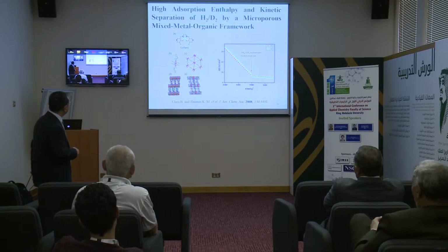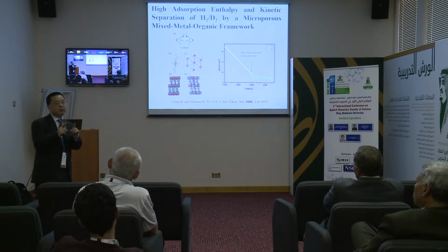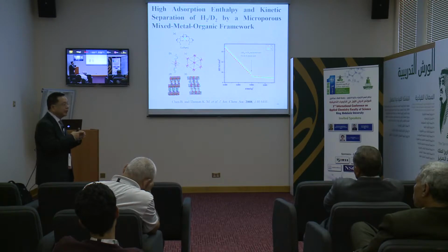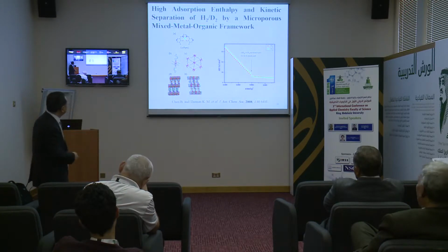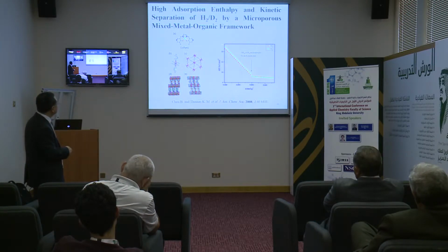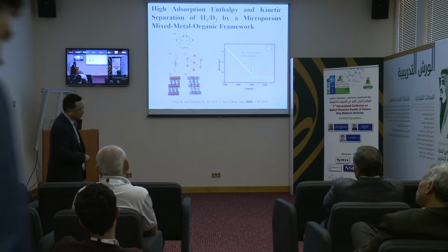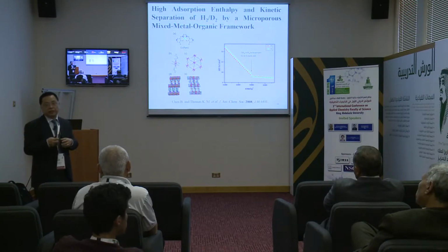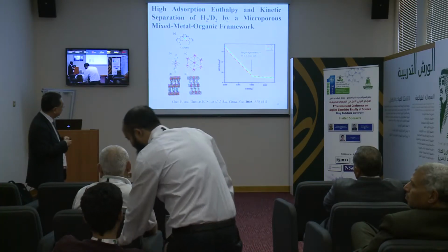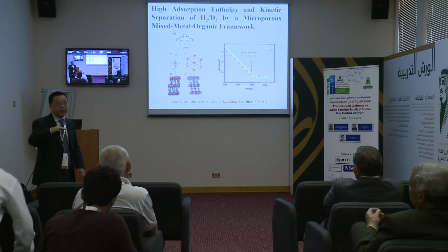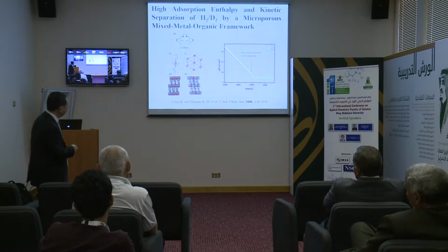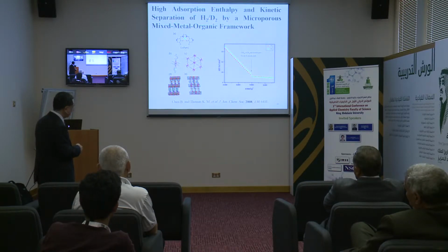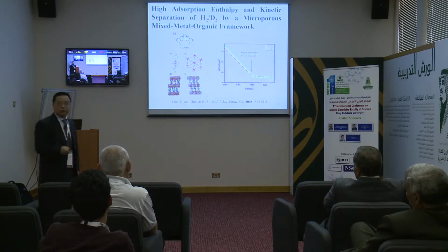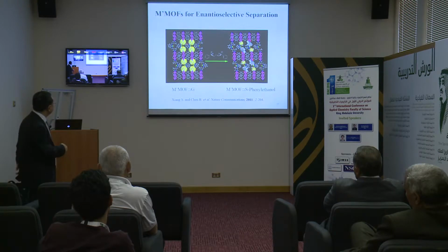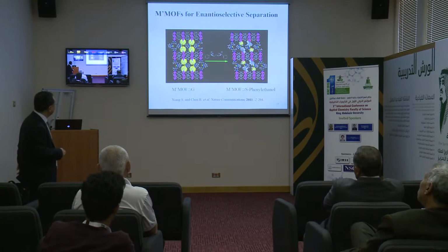One is that each metal site can bind two gas molecules, which is very unusual. Typically an open metal site is easily saturated, bound by another organic linker. So two is kind of interesting. Secondly, the binding energy is kind of high, over 12 kilojoule per mole, because for hydrogen storage, the most challenging issue is the adsorption enthalpy. If it can be increased, then the storage temperature can be increased for hydrogen. So this is one of the challenges. Also, this can be used for kinetic separation of hydrogen and deuterium, because the diffusion rates through the material are different. And you see, we use chiral diamines, and this cavity is chiral and specifically recognizes one of the isomers, so it can be used for separation.